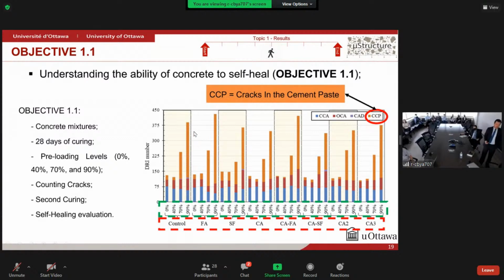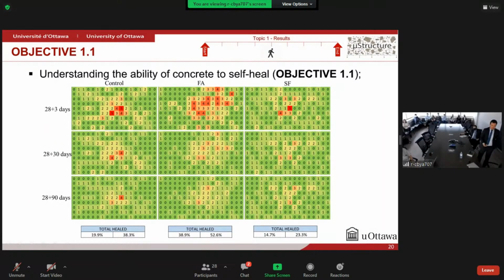After taking the DRI number and counting the amount of cracks in the cement paste, we sealed the polished surface of the concrete, and then we placed them back in an environment to cure again for 90 more days. It's important to mention here that we did not use reactive aggregates for this analysis. After the second curing of 90 days, we then tested again for DRI to check the ability to self-heal of the concrete specimens. And as we can see, only by adding SCMs, the concrete was able to heal 50% of the cracks in the cement paste.